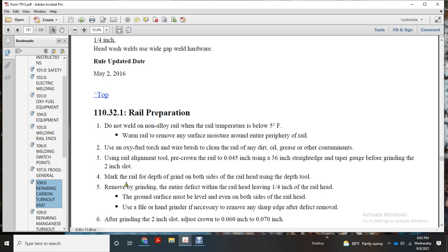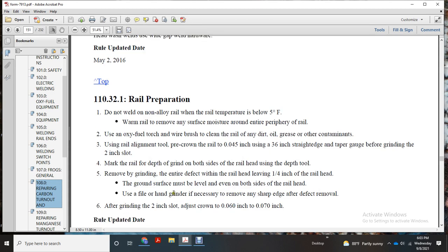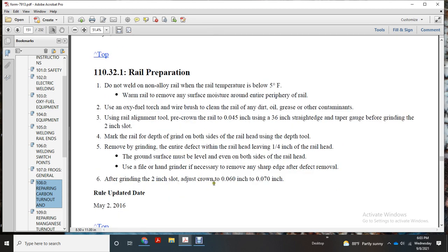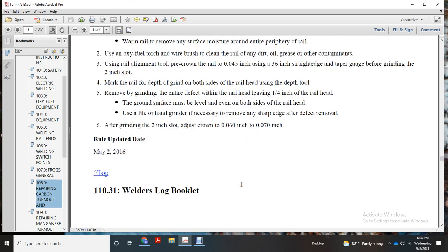Use the depth tool. Remove the defect by grinding the entire defect from the rail head, leaving 1/4 inch of the rail head. The ground surface must be level and even on both sides of the railhead. Use a file or hand grinder as necessary to remove any sharp edge from the defect removal. After grinding the 2-inch slot, adjust the crown to 0.060 to 0.070 inch.